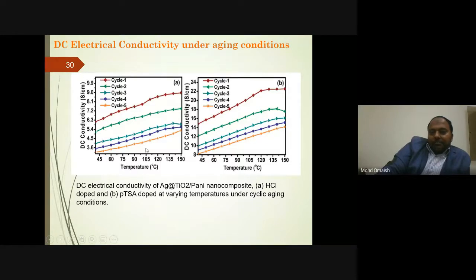And next is the DC electrical conductivity under aging conditions. We studied the DC electrical conductivity of polyaniline under aging conditions, measuring the electrical conductivity from around 35 to 150 degrees centigrade. This is cycle 1, this is cycle 2, and we found that the conductivity decreases. That's one of the major problems, and that's why we add fillers and change dopants and others, to increase the conductivity or increase the retention and stability.